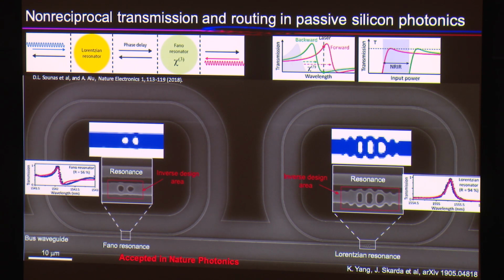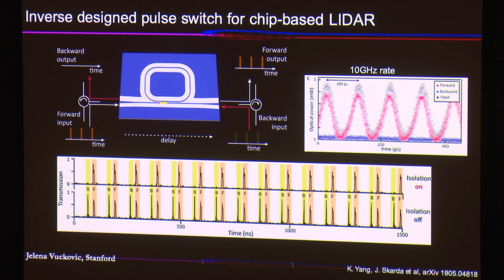And then you can go on and measure this non-reciprocal transmission in two directions. Right? So it's the whole system that behaves in a certain way, not just a single element, but we're designing elements by inverse design. So then we measure transmission. In continuous wave regime, of course, forward and backward, we observe this range, the power range where it exhibits non-reciprocal transmission.